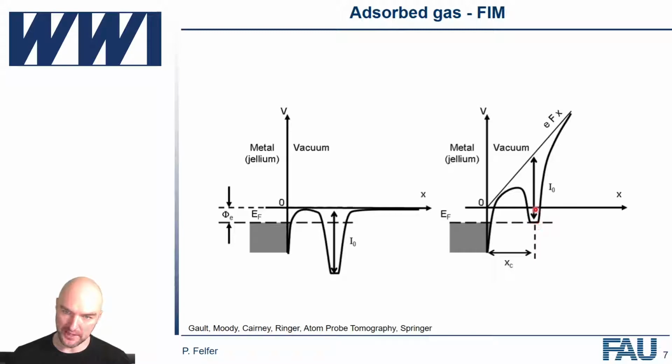to move that potential up high enough so that it can go above the Fermi level of the solid. So if I have a lower field, that critical distance would just move further out, and the probability for that to actually happen would just go down, down, down. And since this is exponentially dependent on the distance, we need to be fairly close, like nanometer range close.